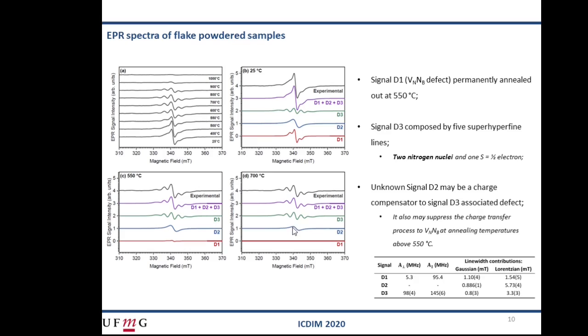The signal also has a good thermal stability, persisting through thermal treatments up to 900 degrees. At this temperature, the EPR spectrum is very, very weak. Another interesting point that occurs in powdered samples is that the VNNB defect is permanently annihilated after the thermal treatment at 550 degrees, and the signal D2 is more stable under thermal treatments in comparison to that of the crystalline sample. In this case, it is not broadened after 500 degrees. Only its intensity slowly decreases until zero at approximately 900 degrees.